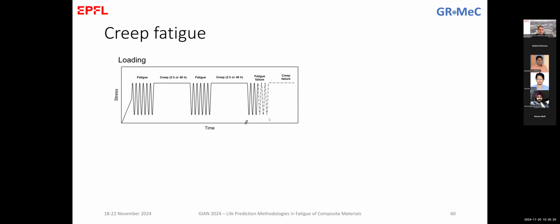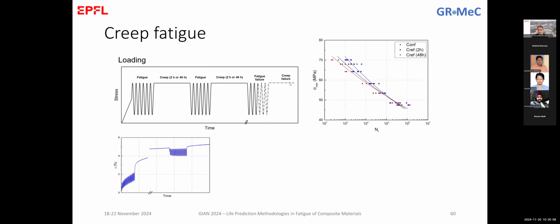So talking about creep, then we realized this creep fatigue testing with the same constant amplitude, keeping at high stresses and so on until failure. And here I have it with dashed lines because in some cases, and this depends on many parameters, depending on this stress level, depending on the time that we kept under load, so these 2 hours or 48 hours, in some cases we had failure during the fatigue loading. In some other cases, we had failure during the creep loading. So the results are shown here.